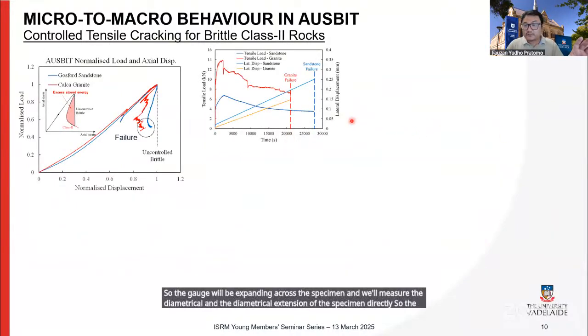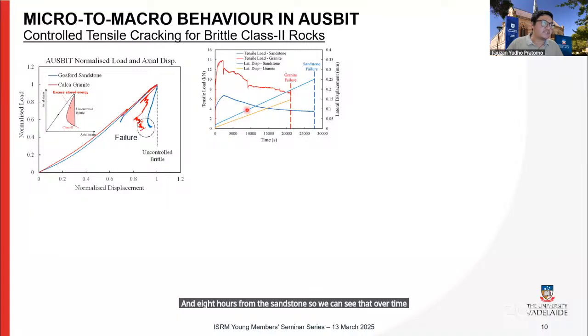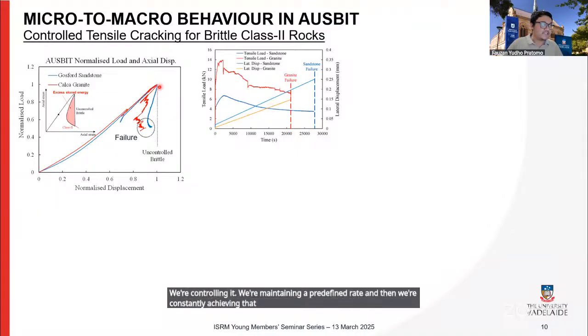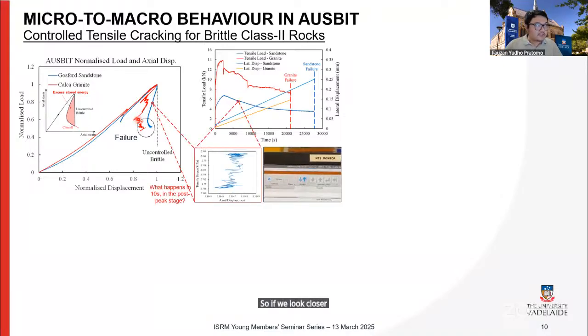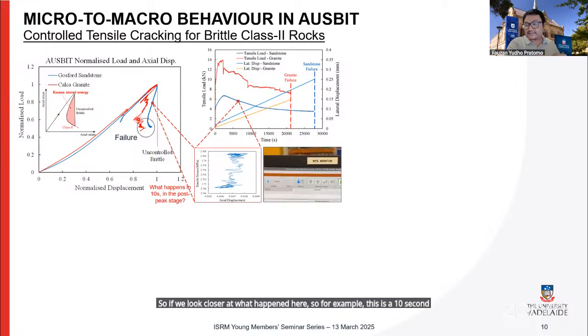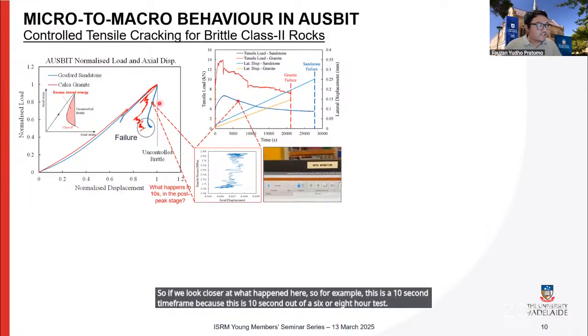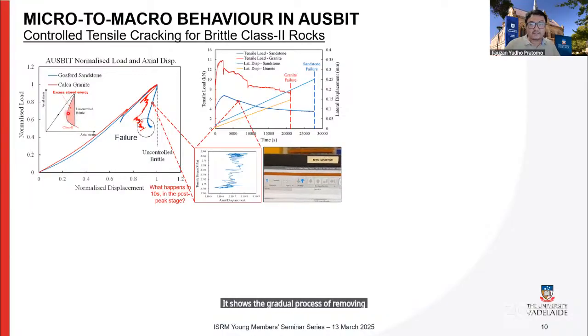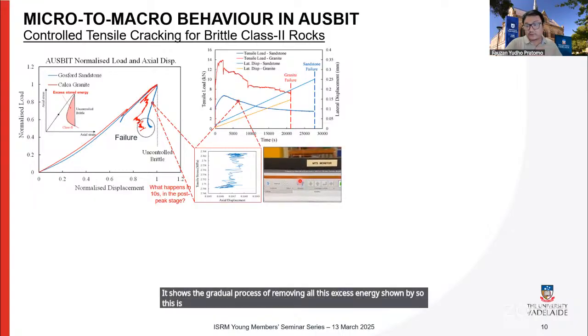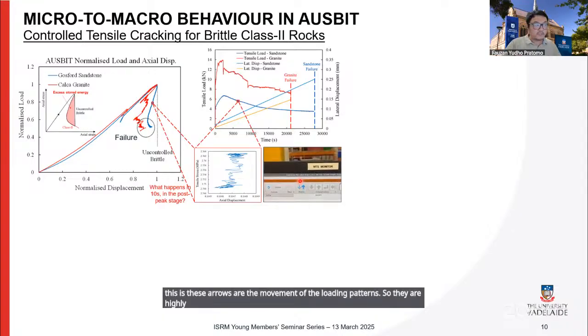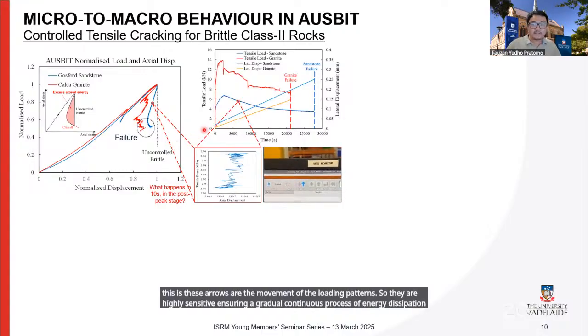So the class 2 response here was successfully obtained. This is after almost 6 hours of testing for the granite and 8 hours for the sandstone. We can see that over time, this is the lateral displacement. We're controlling it, maintaining a predefined rate, and constantly achieving that rate throughout the failure process, which leads to the controlled failure, and we're obtaining this snapback response. If we look closer at what happened here, this is a 10-second time frame, out of a 6 or 8 hour test. It shows the gradual process of removing all this excess energy, shown by these arrows, which are the movements of the loading patterns. They are highly sensitive, ensuring a gradual, continuous process of energy dissipation to ensure that this lateral rate is maintained.